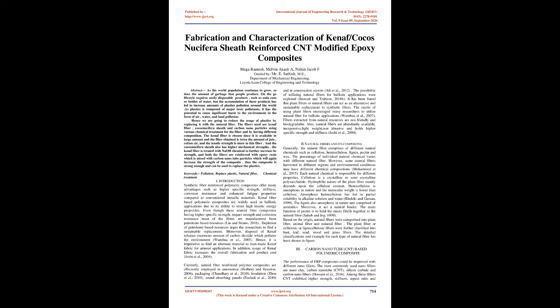The Kenaf fiber is treated with NaOH chemical to further increase its strength. And both the fibers are reinforced with epoxy resin which is mixed with carbon nanotube particles which will again increase the strength of the composite. Thus the composite is strong enough and can be used to replace the plastics. Keywords: pollution, replace plastic, natural fiber, chemical treatment.